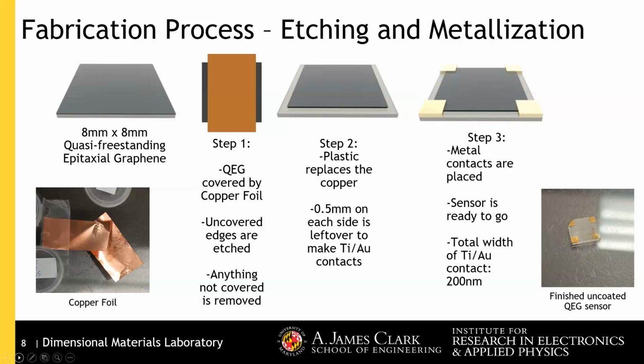In order to actually do the testing and have a conductive layer, you put on these little metal contacts, which are titanium and gold. In total, they're 200 nanometers thick. About 15 nanometers are the titanium, and the other 185 are gold. From there, we run our micro manipulators through it and run a constant current through it. That's where we're going to do our testing. Here's the copper foil we use, and here are our finished sensors. The copper foil one is a little torn up. And this is how it looks at the end of it.